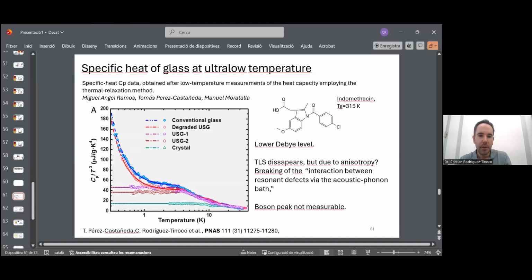With this, let me already talk about low temperature properties. These are heat capacity measurements performed by Miguel Ángel Ramos at the Autonomous University of Madrid. This is indomethacin, remember this prototypical molecule that we started to use when we started to study ultrastable glasses. Here you see the crystal. This is the heat capacity divided by T cubed, the typical representation to observe TLS and the boson peak.